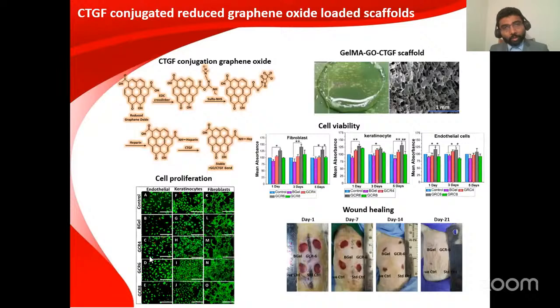And also we are doing growth factor conjugation of scaffolds, especially by conjugating CTGF, that is connective tissue growth factor, with reduced graphene oxide. Reduced graphene oxide was used as a carrier material, which facilitated the controlled release of the CTGF. Also, graphene oxide has a good angiogenic response. So we found that the cell proliferation and everything was higher when an optimal concentration of the graphene oxide and also the CTGF was present in the scaffold. Also, we found higher diabetic wound healing.